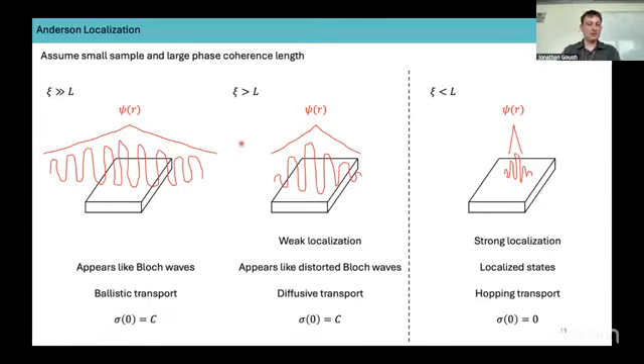Now, as we increase the disorder, the wave function shrinks due to the contribution of these looping paths. And we now notice that the wave function is still bigger than the sample size, but it's beginning to shrink. So this would be called the weak localization regime, where interference, self-interference effects become more obvious in your transport measurements. So the wave function would appear like a distorted Bloch wave. Transport's most likely diffusive, but it still remains a metal because the wave function extends beyond the system.